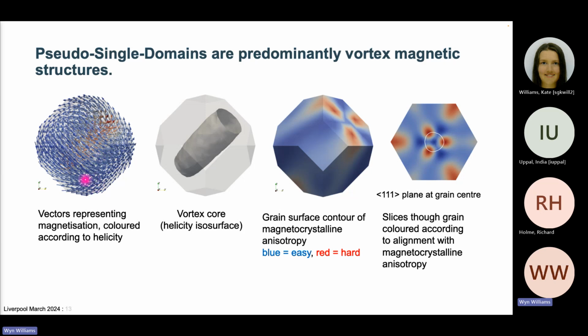And the grain size range, as we'll see shortly, is at least an order of magnitude larger than the single-domain grain. They have larger remanences because they're larger grains. So the chances are, in any paleomagnetic sample you have, these types of structures are a dominant or a significant contribution to the remanences that you're measuring.